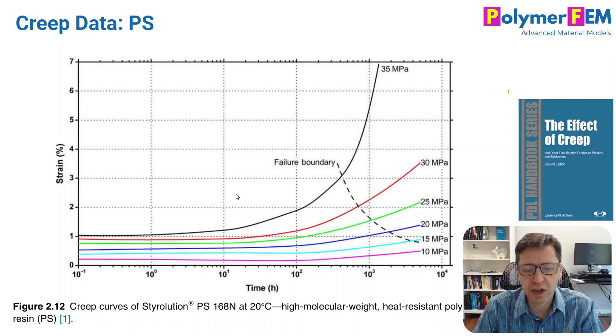I calibrated the TNV material model to the polycarbonate data — uniaxial tension and uniaxial compression — with a yield stress around 60 MPa. The material is viscoelastic, and running the calibration shows the model predicts the response reasonably well, with about 11% error. The focus, however, is not the stress-strain prediction but rather how this model predicts creep rupture. I created creep load cases with specific stress levels and time columns to explore this, using virtual test data.